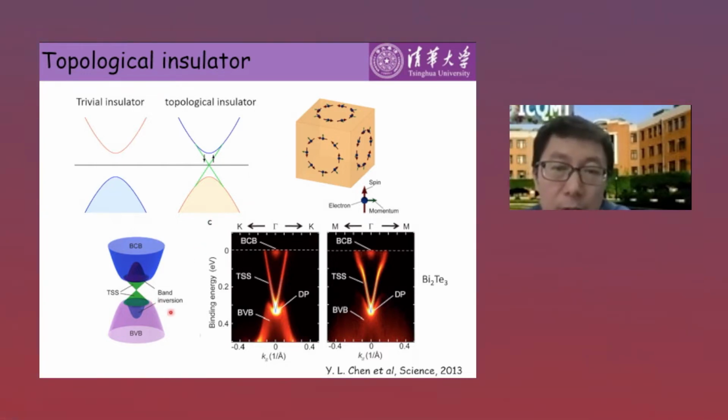In a prototypical topological insulator, such as bismuth telluride, the bulk band topology guarantees the existence of a two-dimensional topological surface state with gapless Dirac dispersion, which can be directly visualized using ARPES. Time reversal symmetry plays a crucial role in the protection of the gapless Dirac surface state.